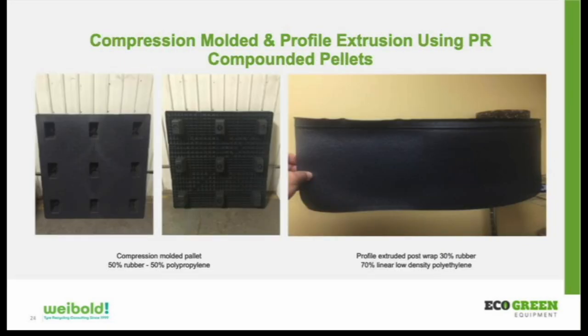Then compression molded or extruded parts. The pallets on the left were 50% rubber, 50% plastic. Again, we've created a plastic rubber pellet, run it through the extruder that goes to make these pallets, and we were able to get a very high content. Now, why would you want 50% rubber in a pallet? You probably don't, because it made the pallet very flexible. The idea was to show that we could make a very large part, like a 4x4 pallet, with a very high blend of material. This particular pallet had basically four injection points.